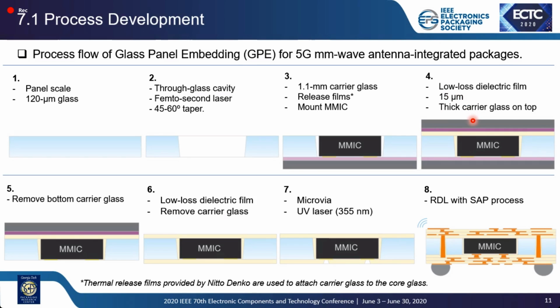And we also attached a thick glass carrier again. And we removed the bottom side glass carrier and laminated low-loss polymer, again Taiyo Zeristo, and removed the top side glass carrier. And we drilled micro vias for electrical connections, and RDL formation was stalled because of the COVID-19 situation. So we're going to resume this after the lab reopens.